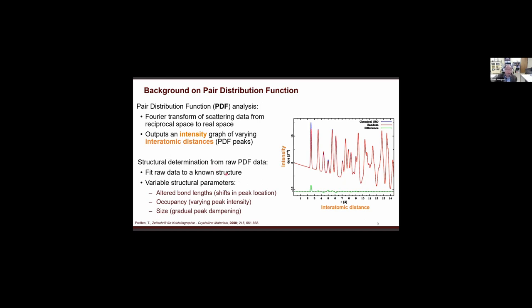For example, we know there's zirconia, in the cubic phase, and then we can fit that pretty well. Also, there are variable structural parameters, some of which are similar to X-ray diffraction or crystallography, such as the bond length, which shifts the peak locations. The occupancy changes the peak intensity, and there's also the size of the domain. For example, some may be 10 angstrom, some may be 7 angstrom, and it shows in the gradual peak dampening. We'll see that in some examples later on.